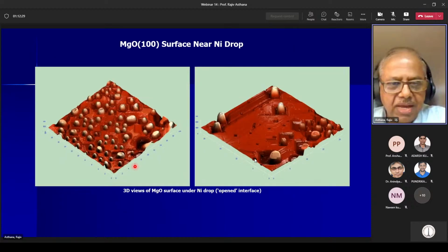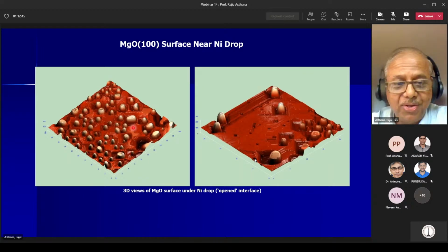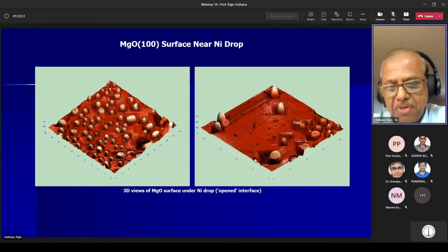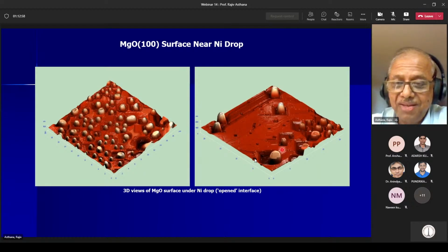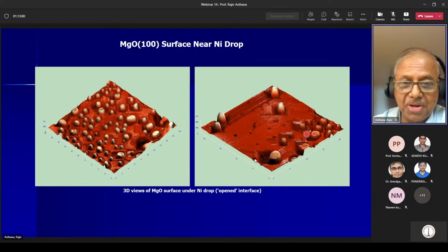What we saw was that the bigger liquid droplet, which was about 2 millimeters in diameter, broke up into little daughter droplets, and those droplets actually reside inside these little dislocation edge pits. So when you push the droplet on the surface like that, the teeny micrometer-sized droplets actually break off from the mother droplet and they get stuck in these little dislocation pits.